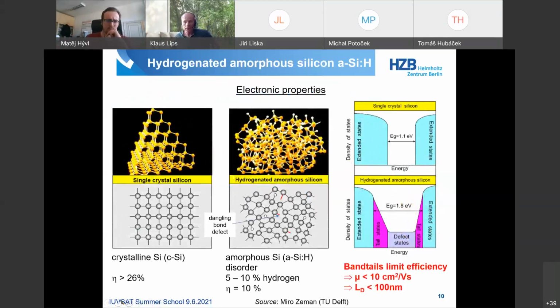Okay, this amorphous silicon is quite an interesting material. I've been working in this field now, I would say, over 30 years. And that's also where I met Antonin many years ago. And the main feature of this amorphous silicon is that we have basically a local order. The order around any silicon atom within that amorphous silicon still has the near order of silicon, mainly a silicon atom, which I'm highlighting here, is still bonded or mainly bonded to 4 other silicon atoms, but the nearest and second nearest and third nearest neighbors, you get complete disorder.